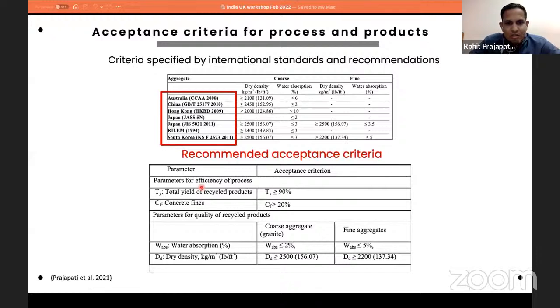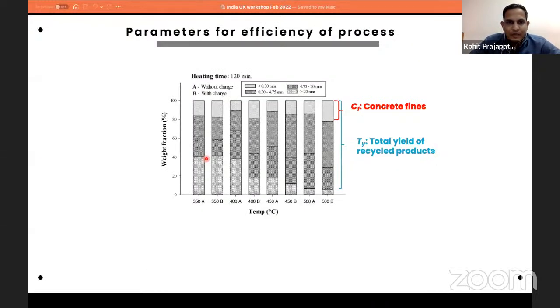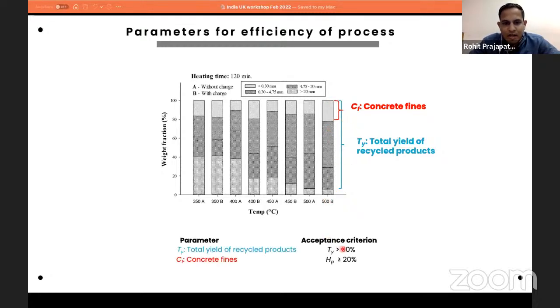So first let us understand the parameters for the efficiency of the process. Here I have plotted the weight fraction of different sizes of particles. In the first box you have concrete fines, which are particles less than 0.3 mm, and then you have fine aggregate, coarse aggregate, and the last box is particles above 20 mm in size, or you can say just unprocessed material. The concrete fines will be the amount of particles less than 300 micron, and concrete fines together with coarse and fine will be considered as the total yield. The total yield should be more than 90%, and the concrete fines should be less than 20%.